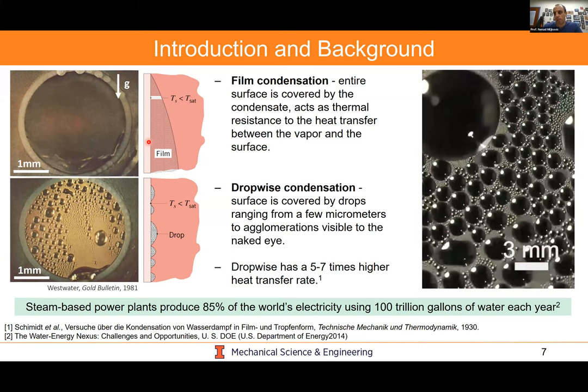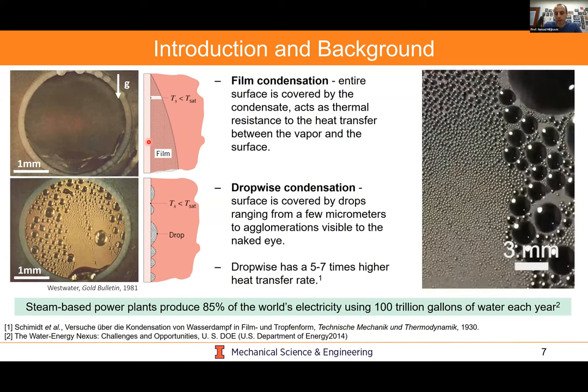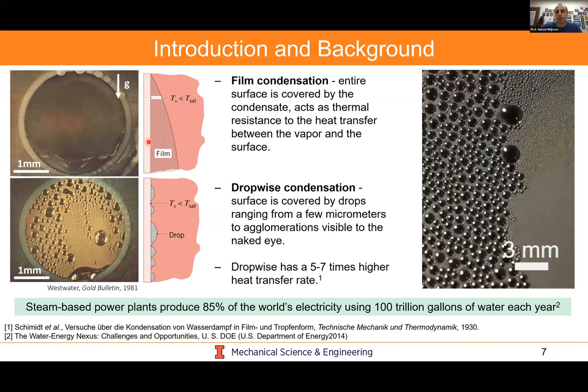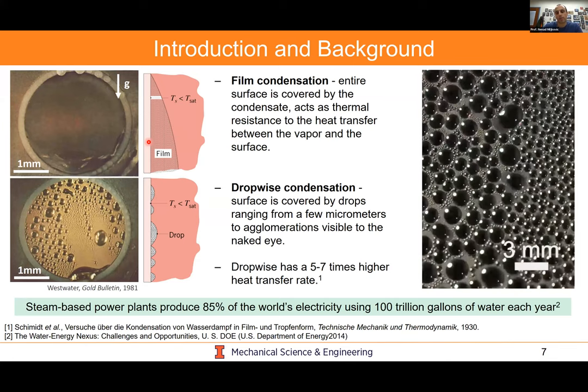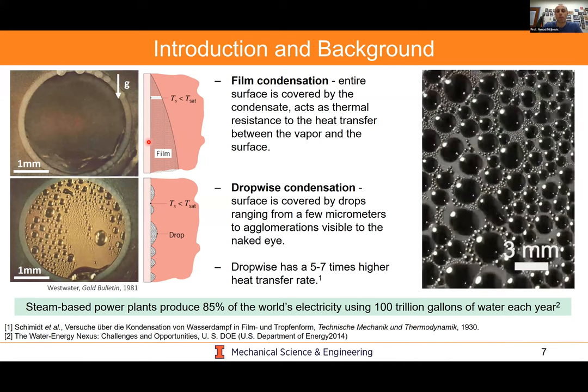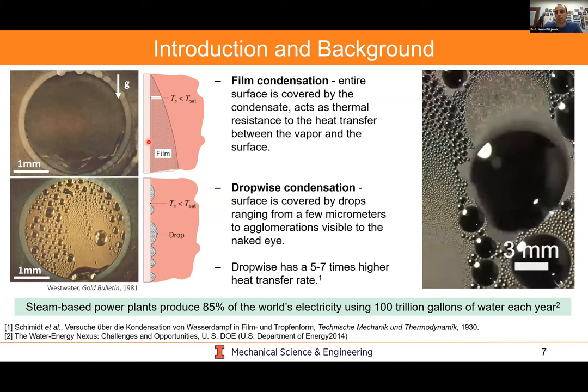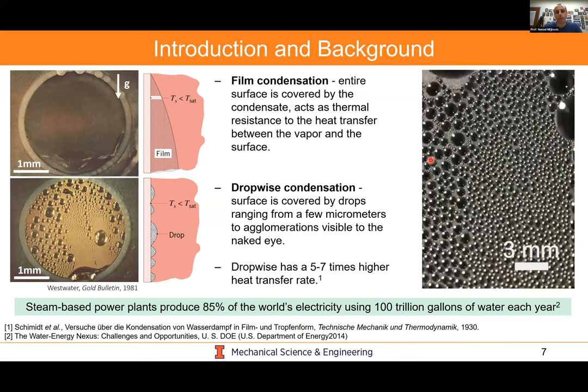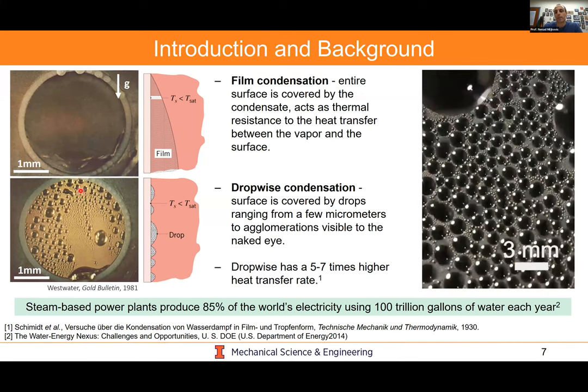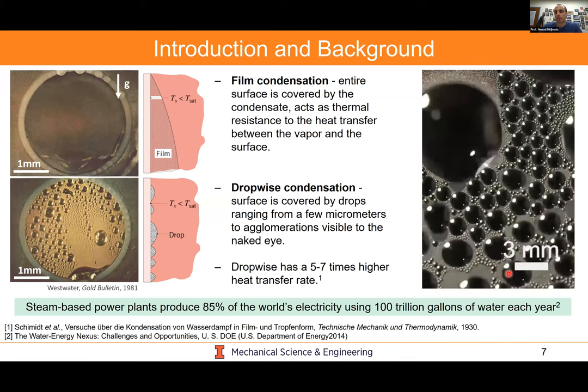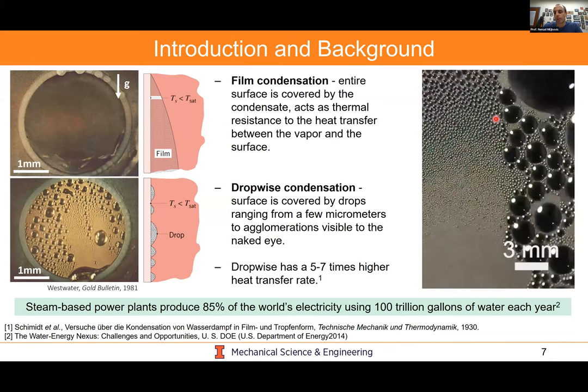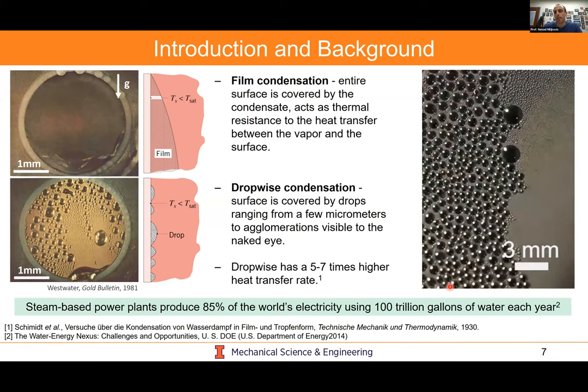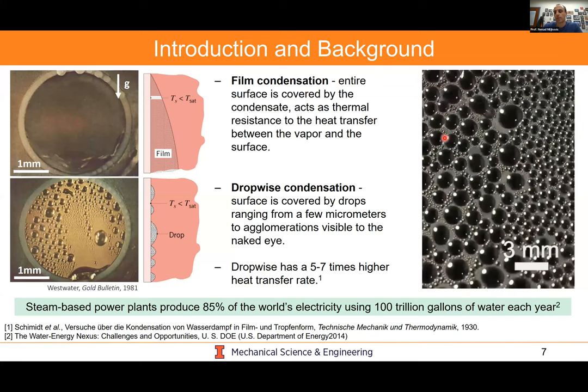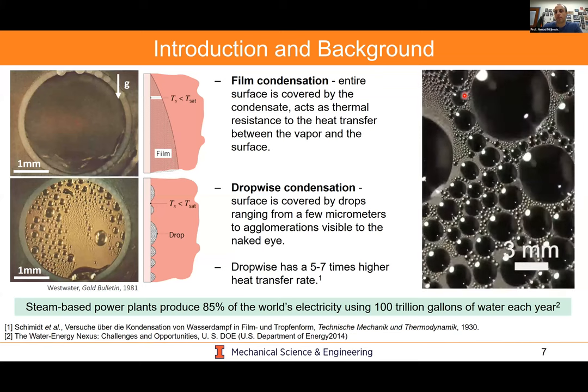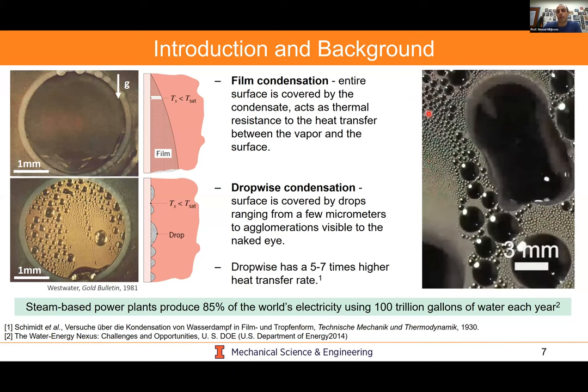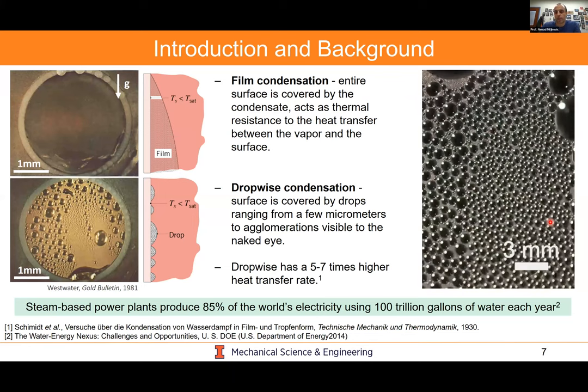Now, well over 80 to 90 years ago, a gentleman in Germany by the name of Schmidt discovered that if you take one of these tubes and just spread animal fat on the outside of the tube, you're going to see something called dropwise condensation. And you see this on the video on the right here, as well as this bottom left image, where distinct droplets form on the surface, they coalesce, they grow, and eventually they shed from the surface and are removed. And it's actually this dropwise condensation process, this renucleation, this clearing of the surface, which makes this heat transfer phenomenon 10 times more efficient than film-wise condensation.